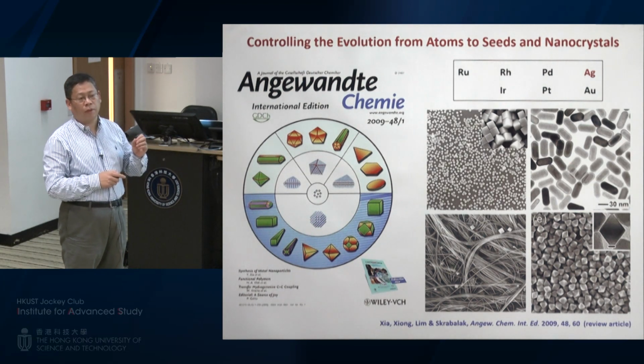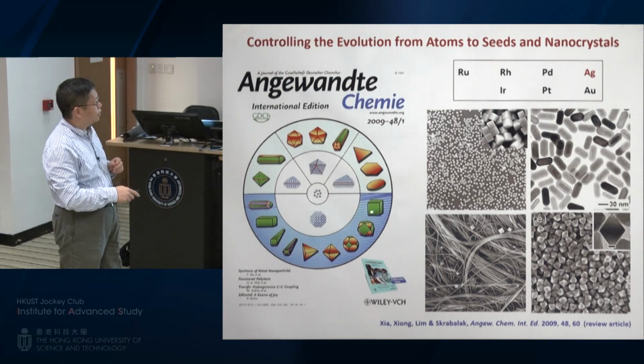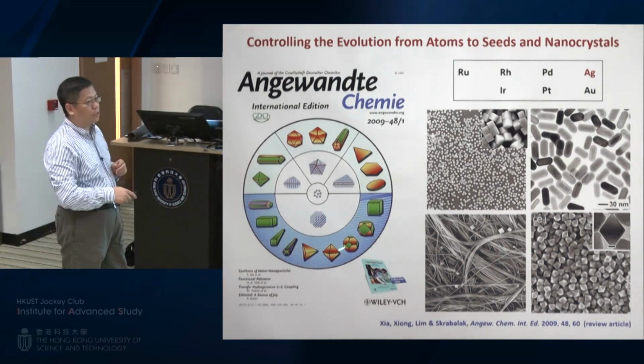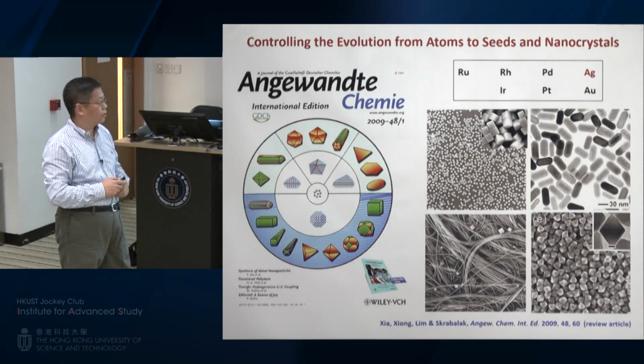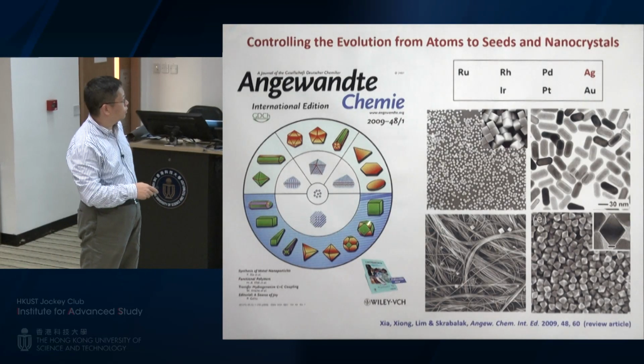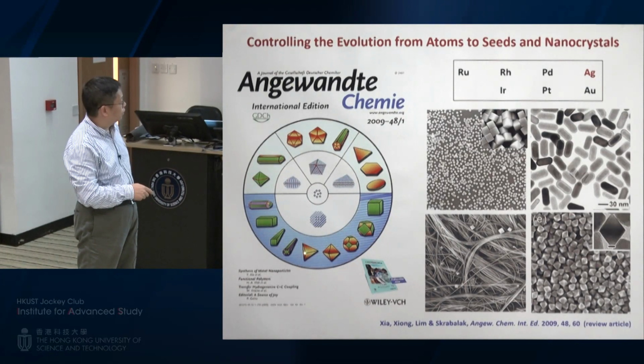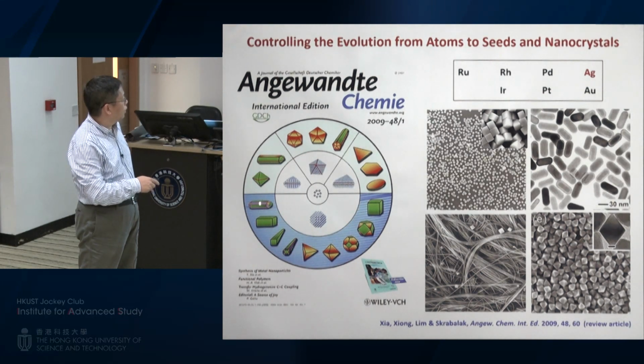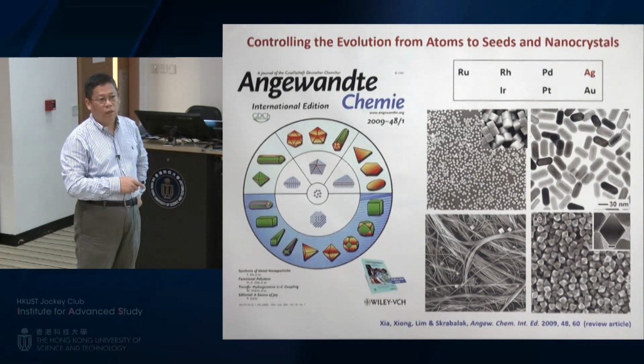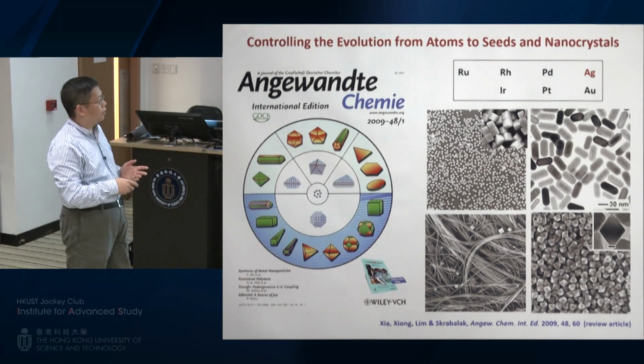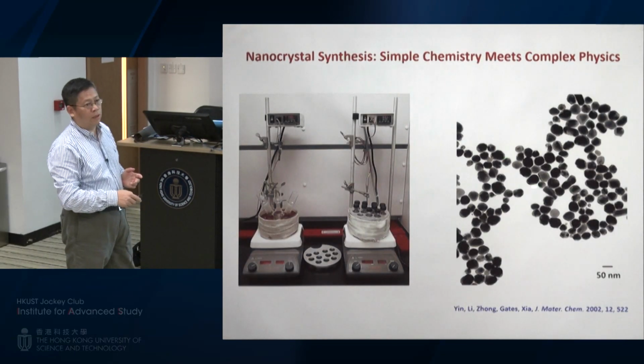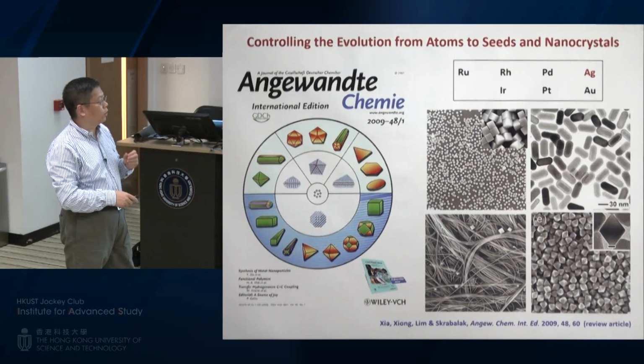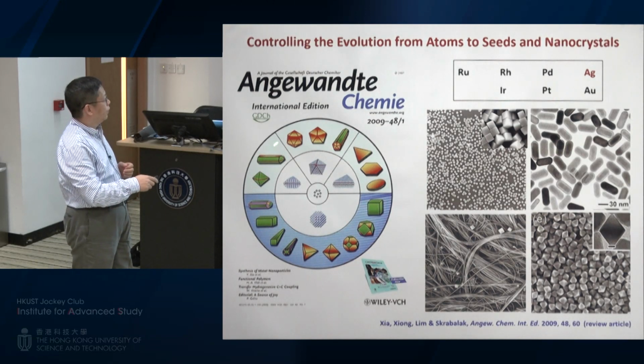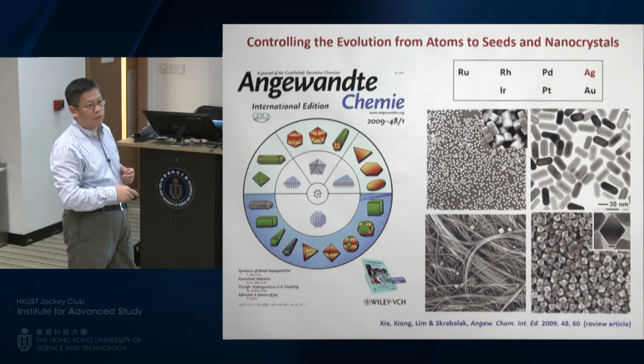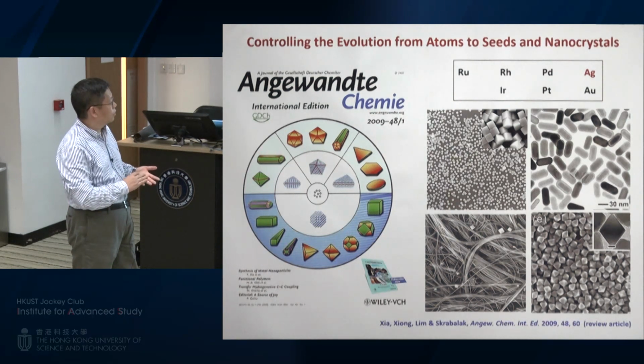And then from the same type of seed, when they grow in size, they also end up in different destinations. Like they can become cubes, they can become octahedra, tetrahedra, and so on and so forth. And some of them may take even elongated morphologies. So now you can easily understand why this sample looks like this. Because if you don't really do good control, you are going to make a mixture of all these particles. So that's why it's so polydispersed.